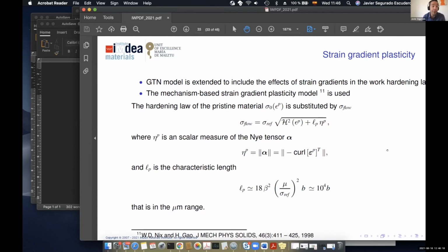So if we introduce that into the model, which is something that we're going to do in the near future, because we can have delamination using phase field fracture localized on the boundary. That's something that the group of Dirk has also worked on. You can put all the mechanisms into the same model. And in this case, as you suggest, volume fraction will play a role, because you can change from one mechanism to the other. Small volume fraction will probably lead to just damage in the matrix, and you will get what I have shown. But for larger volume fractions, you promote particle fracture, and then you will get the other effect in ductility. That's absolutely right.